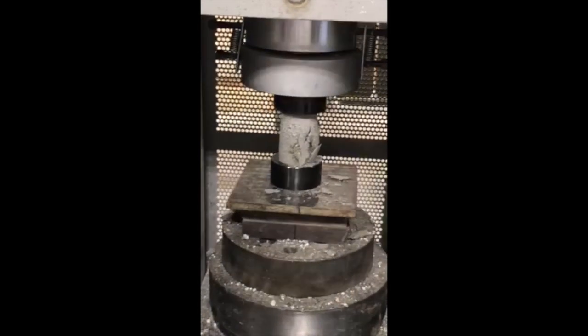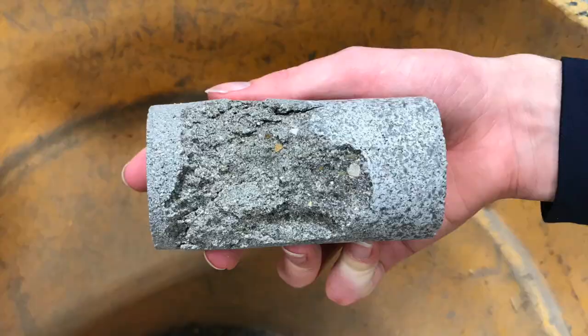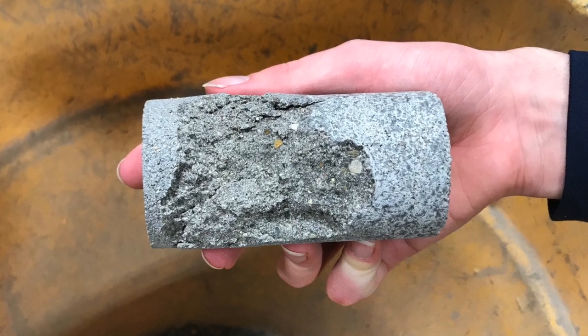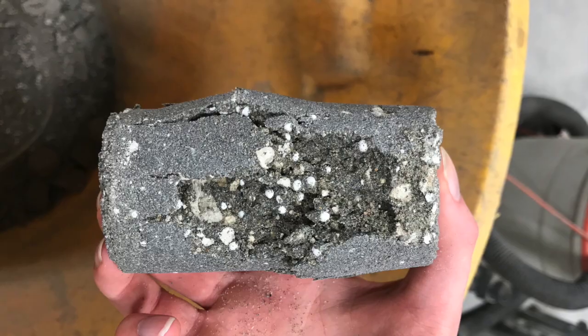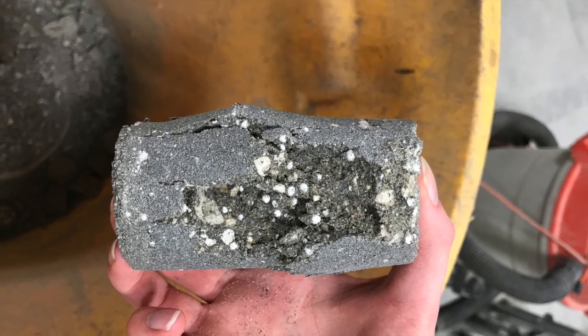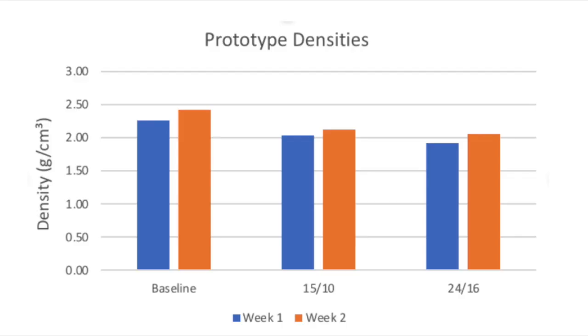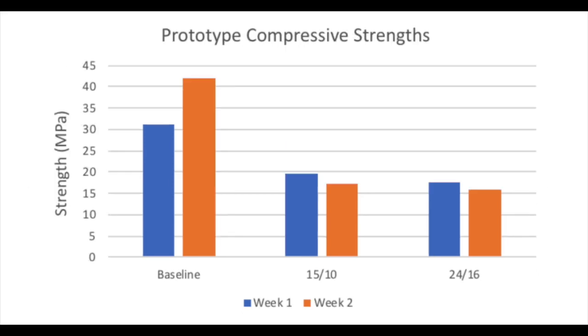Your samples will be loaded into this machine and will be tested until failure. Record the maximum load displayed on the machine for all of your samples. You can use the dimensions of each sample to calculate density. Similarly, cross-sectional area can be used with max load data to calculate compressive strength for all of your samples. With this, you have successfully mixed, casted, and tested concrete composite samples and can decide whether they are successful in meeting the mechanical characteristics that you desire.